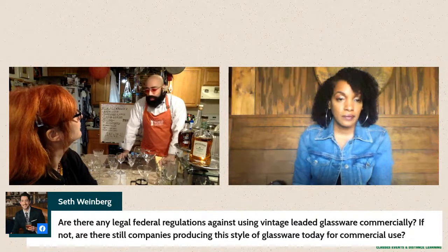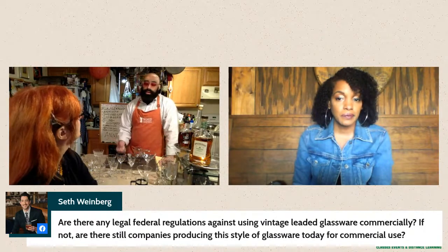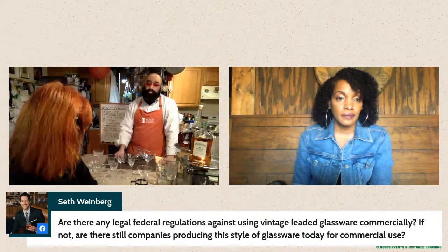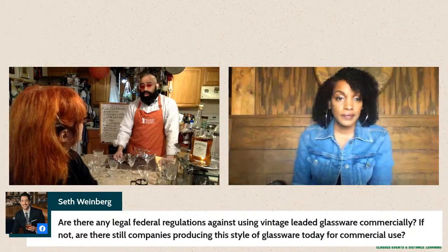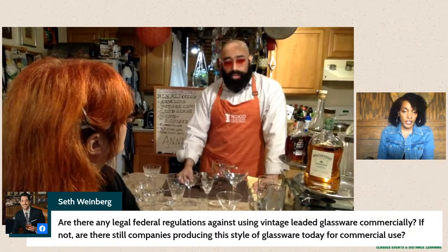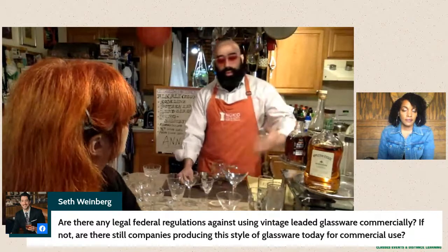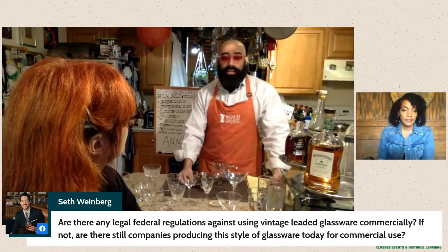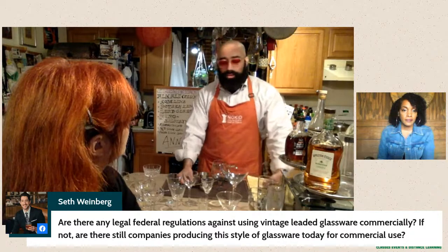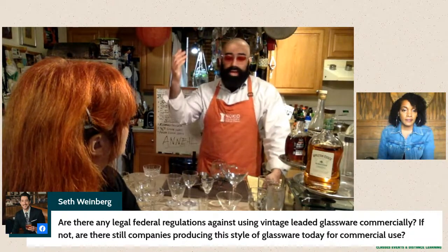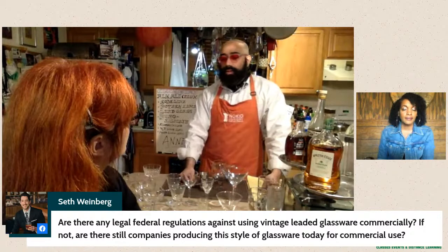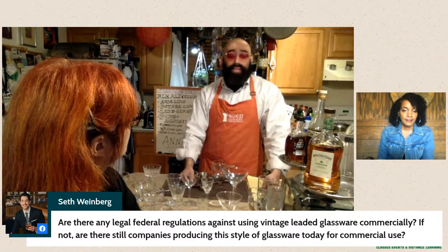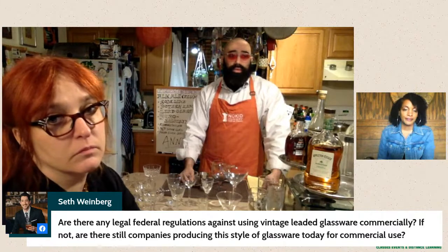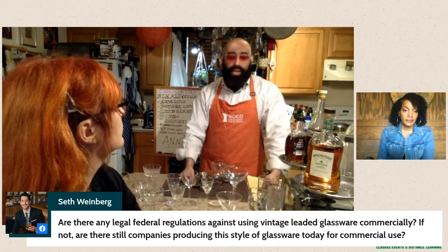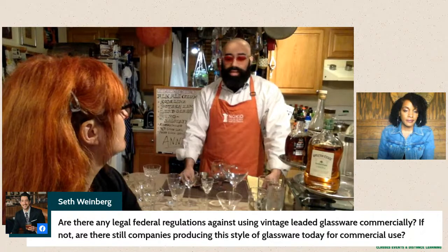However, scientifically speaking, the amount of lead that can potentially leach out of lead glass depends on a couple of factors. First of all, the percentage of lead that's used in the process. Just like we said earlier, you could get 20 or maybe 24% lead in the batch. That's kind of normal. There are other producers that go up as high as 30 or more percent, and you can usually tell those pieces by their sheer weight. The higher percentage lead glass is very heavy for its size. So that's one of the dead giveaways.